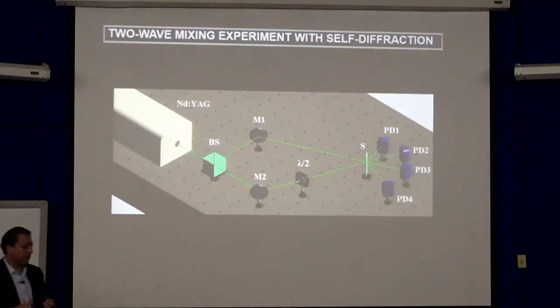So let's suppose that the direction of the beam is in this direction, and the direction of polarization is perpendicular. The wave plate allows you to rotate this vector. Eventually we put some photodetectors for measuring the transmitted beams and the self-diffraction beams, and the self-diffraction effect is going to be dependent on the nonlinearity that is characteristic of the material. For instance, the material can change the physical mechanism of nonlinearity from thermal to electronic to molecular orientation or electrostriction. So we can test with this technique the physical mechanism responsible for the nonlinearity of the sample in the system.